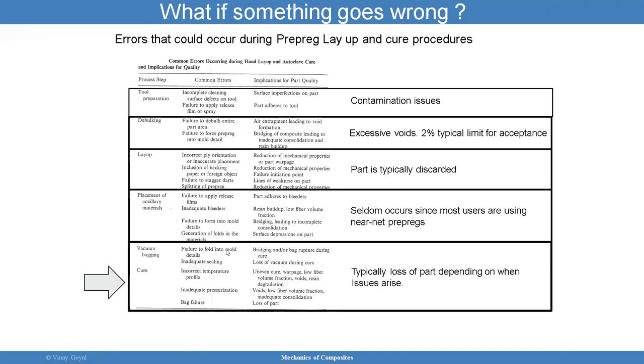Vacuum bagging: failure to fold into mold details, inadequate sealing, incorrect temperature profile, inadequate pressurization, bag failure. All these things will lead to loss of a part, voids, uneven cure, loss of vacuum. So you have to look at each of these and look at the implications. Inadequate pressurization is obvious: voids, low fiber volume fraction, high void content, porosity. Incorrect temperature profile: uneven cure, low fiber volume fraction, voids, resin degradation. Inadequate sealing: loss of vacuum, and so forth. So these can lead to typical loss of the part depending upon what issue arises, and we have to be cognizant of that.